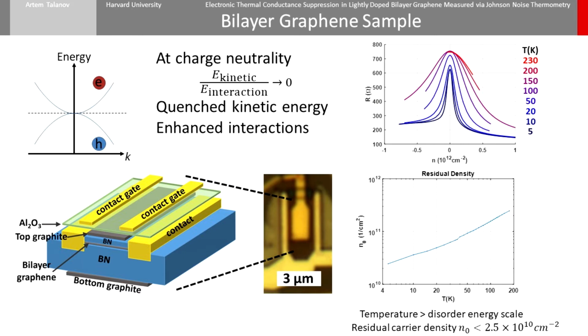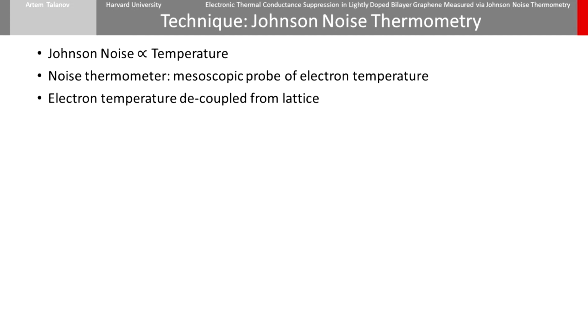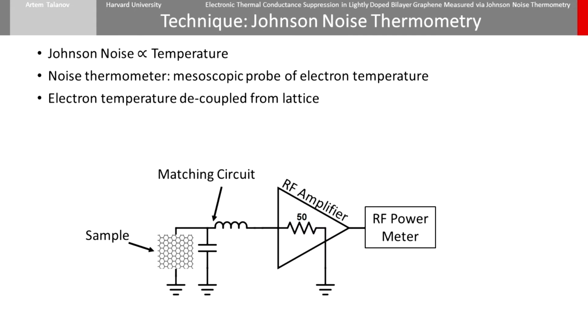The temperature scale of disorder in the sample is below 5 Kelvin, and the disorder residual density is below 2.5 times 10 to the 10 per centimeter squared. In our measured temperature range, we are thus never limited by disorder. I will briefly discuss our measurement technique. To measure the temperature of the electrons, we measure their Johnson noise with a circuit similar to this simplified one shown here. The reactive matching circuit improves noise coupling between high-impedance devices and 50 ohm amplifier inputs.